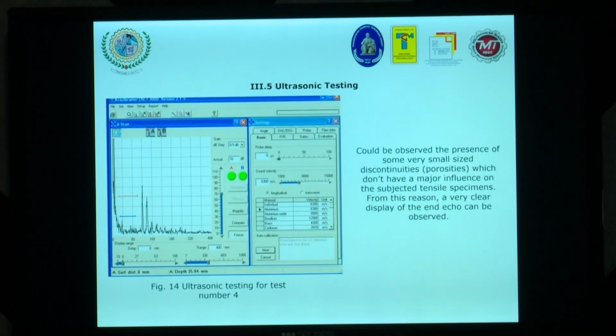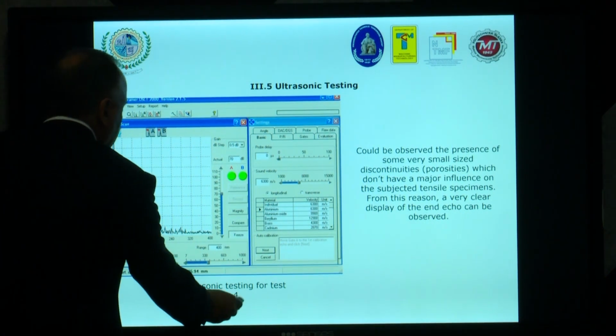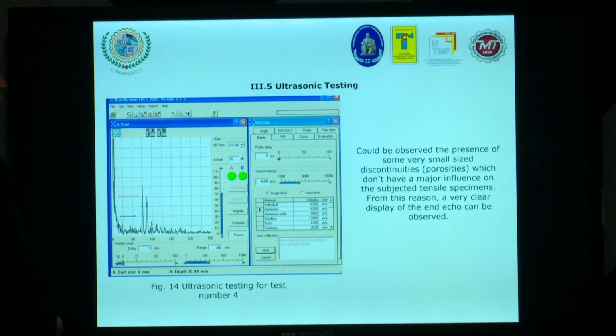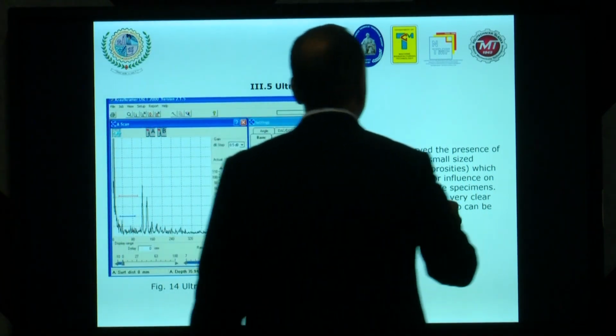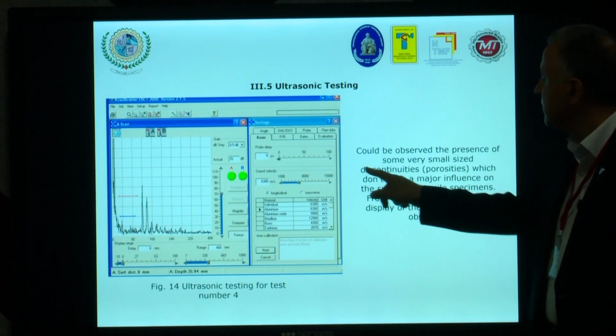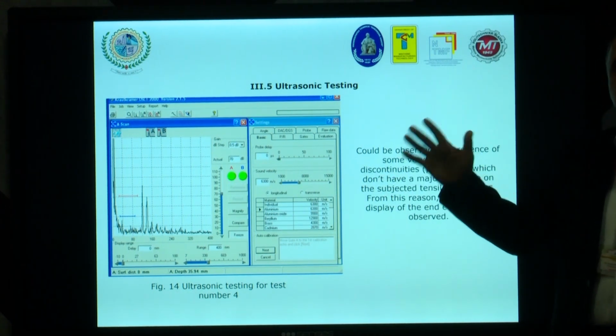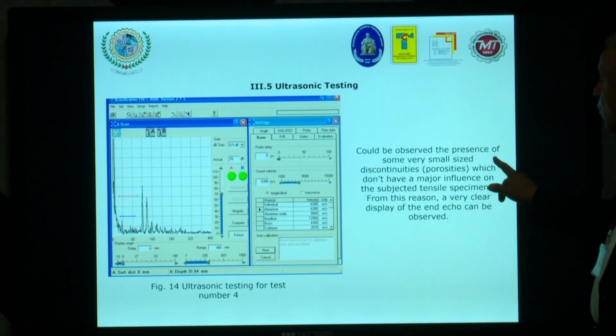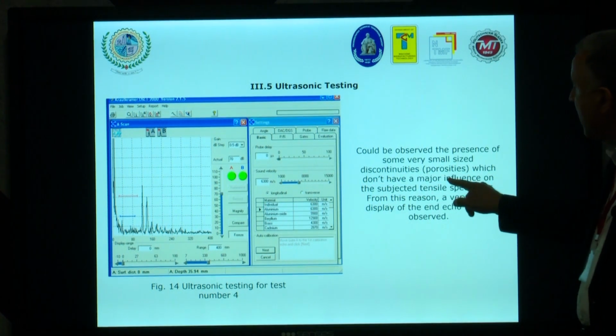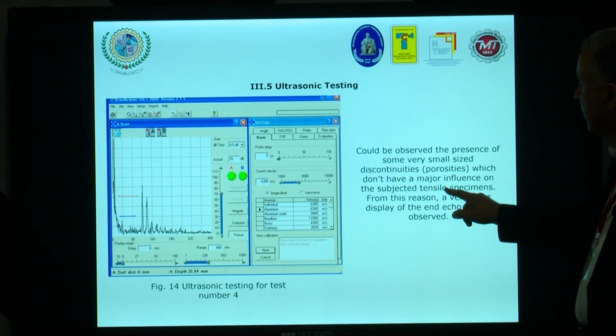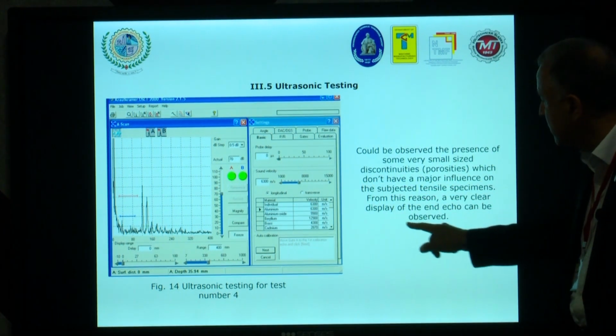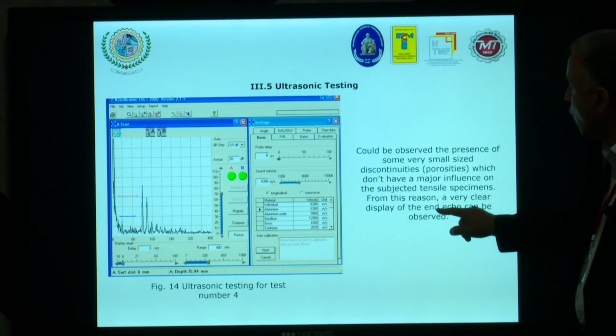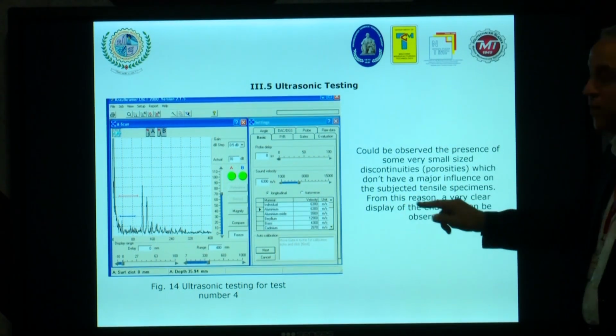And of course, ultrasonic testing. We made the ultrasonic testing also for experiment number 4. And here could be observed the presence of some small, very slight discontinuities. I mean, maybe some porosities, which do not have a major influence on the tensile specimen. Because of this, a very clear display of the end echo can be observed.